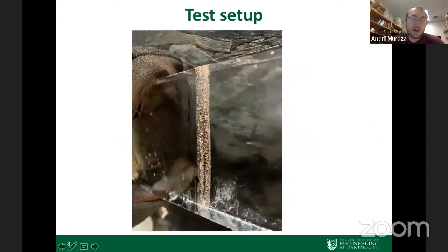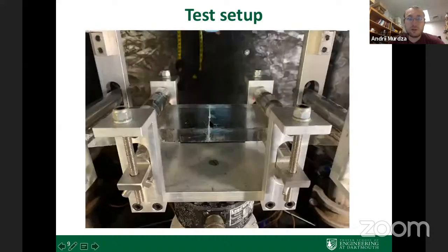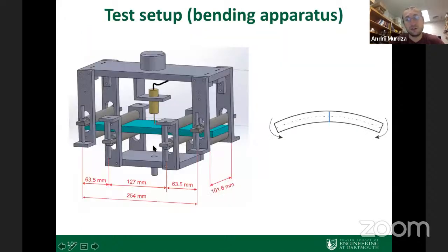After freezing, we could see this freeze bond in the sample. Then we placed the specimen with the freeze bond into the 4-point bending apparatus, as you can see here. One may ask why we wanted to simulate this bond vertically. The reason is that ice floes sometimes break vertically, making a vertical fracture, and then later they refreeze. These ice floes are subject to ocean waves, to cyclic loading, and so we tried to simulate this simple situation.